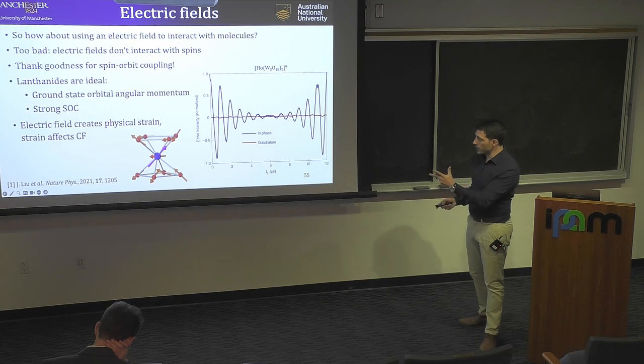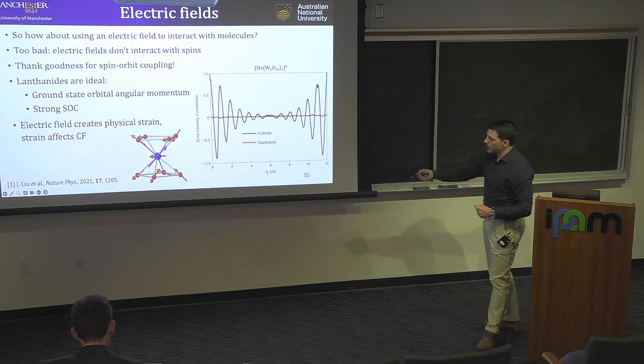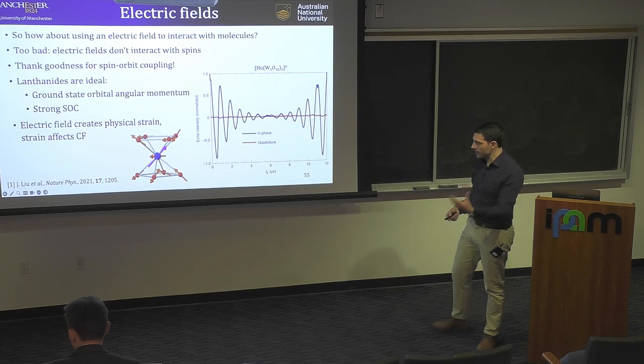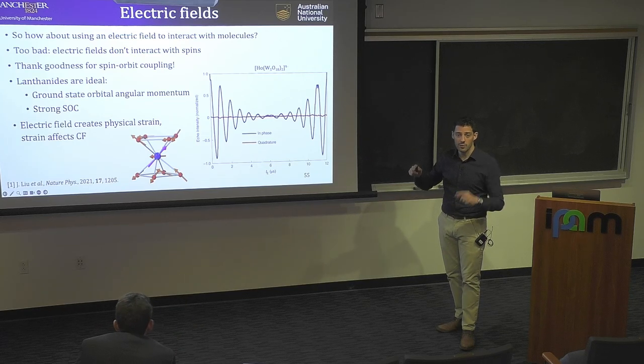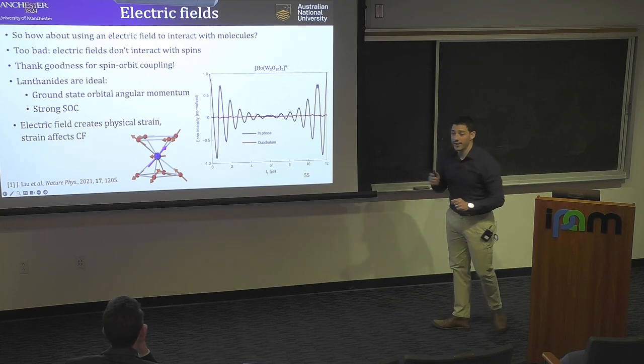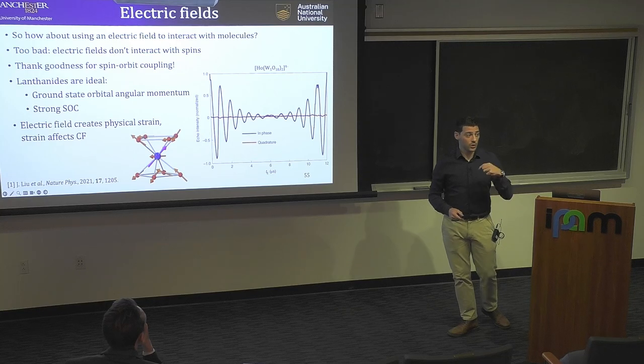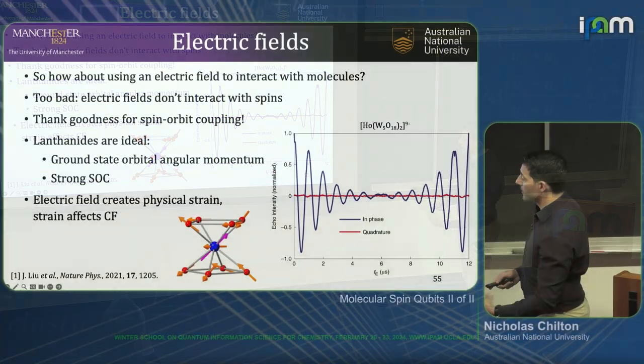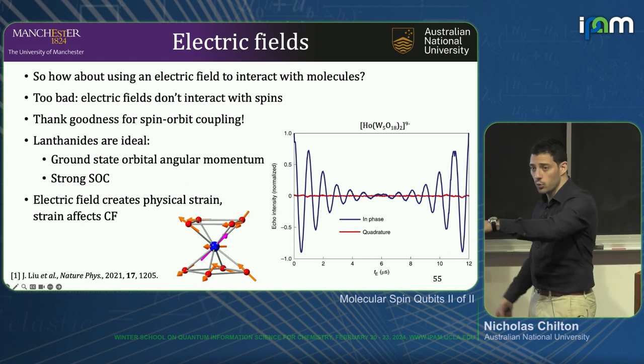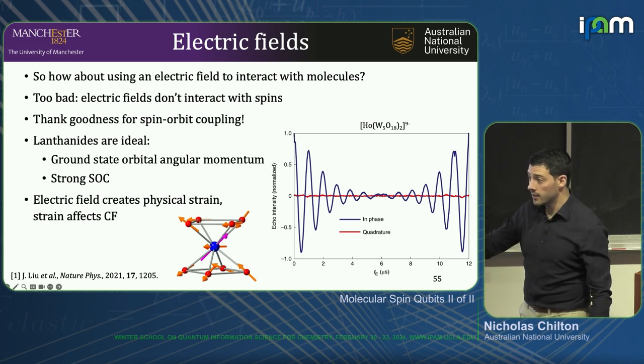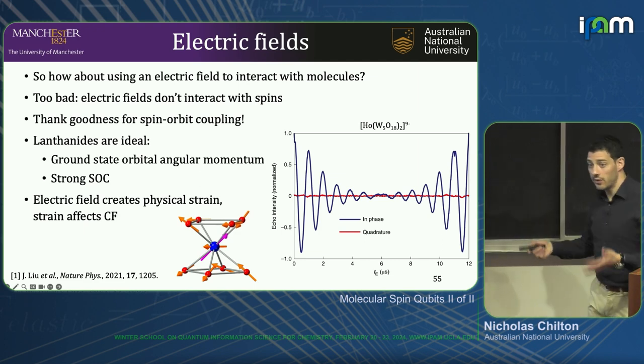Here's an example: the same holmium polyoxometallate, in work done with Arzhang Ardavan at Oxford. They applied an electric field to induce a strain — because you have a breaking of inversion symmetry, there's a permanent dipole in the condensed phase. Applying an electric field strains the atomic positions, perturbing the symmetry and crystal field potential, thereby manipulating the eigenstates. This allows coherent control: during the free evolution period of a Hahn-echo experiment — after your pi/2 pulse — you apply an electric field pulse, and you can show that the duration of that pulse is coherent. You can coherently manipulate molecular electron spins using electric fields.